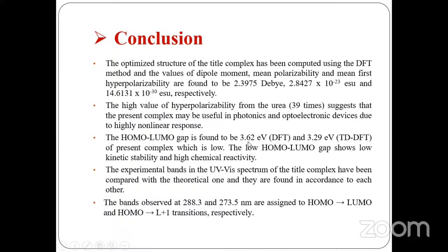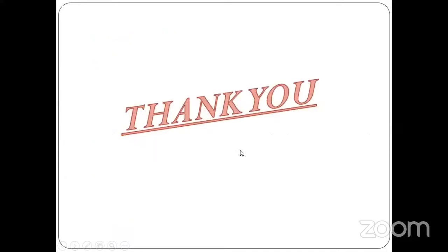The HOMO-LUMO gap from the DFT is found close to that from the TD-DFT calculation. This low HOMO-LUMO gap shows low kinetic stability and high chemical reactivity. The experimental band in the UV-visible spectrum of the title compound has been compared with the theoretical, and they are found in accordance with each other. The bands observed at 288.3 and 273.5 nanometer are assigned to the HOMO to LUMO and HOMO to LUMO plus 1 transitions respectively.